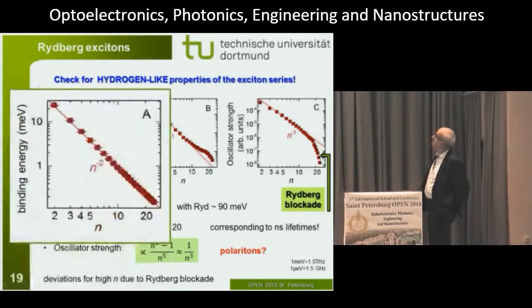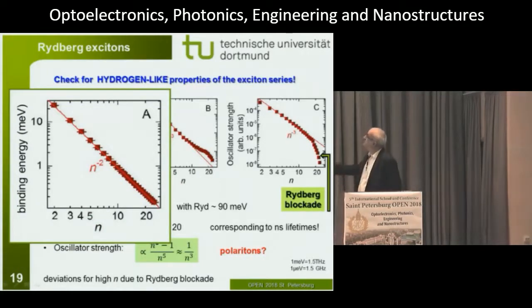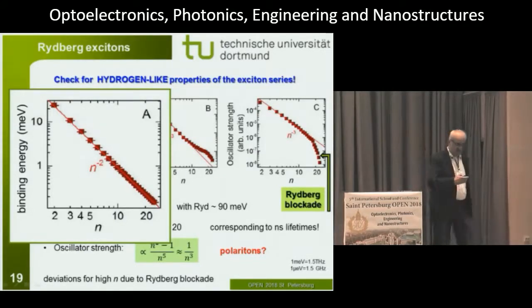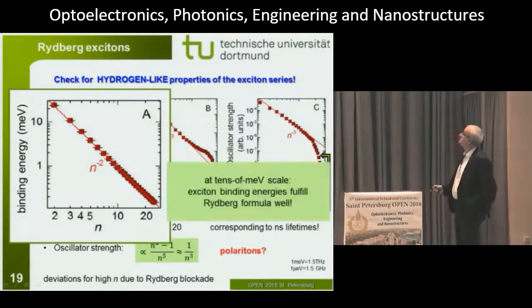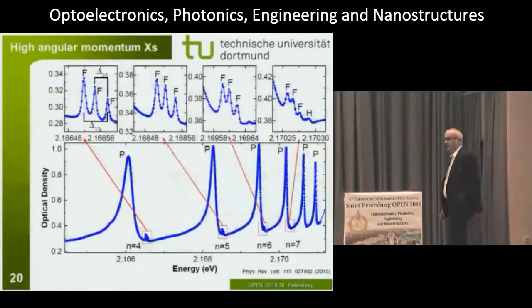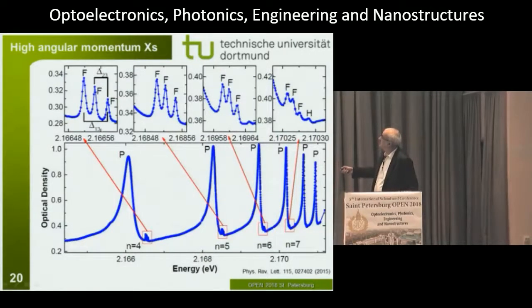Okay, so then you can elaborate on the properties of these excitons. Without going into details, you can check, for example, the binding energy, and you indeed find that the binding energy, at least with this resolution that we have here, follows an n to the minus 2 law, but only on this energy scale and with this resolution. If you look a little bit more into details, this is basically a close-up of the spectra that I showed you already. The dominant features here are the p-type excitons, n equals 4, 5, 6, 7.